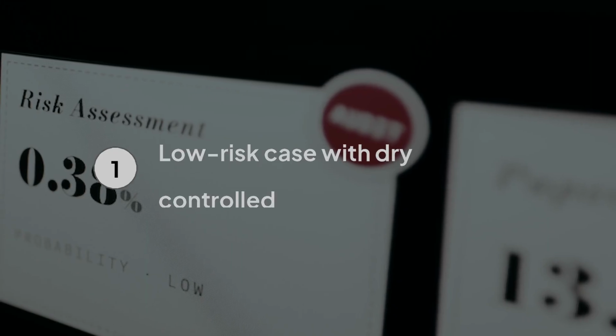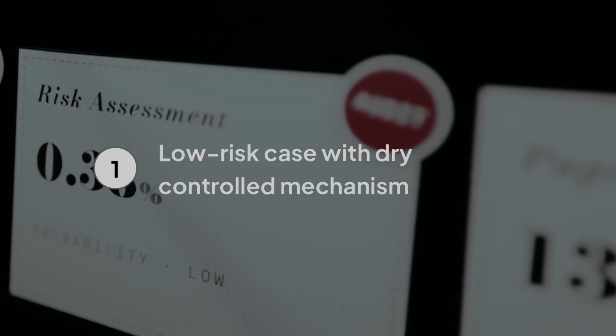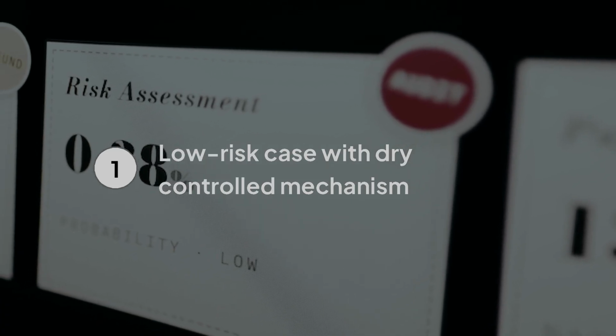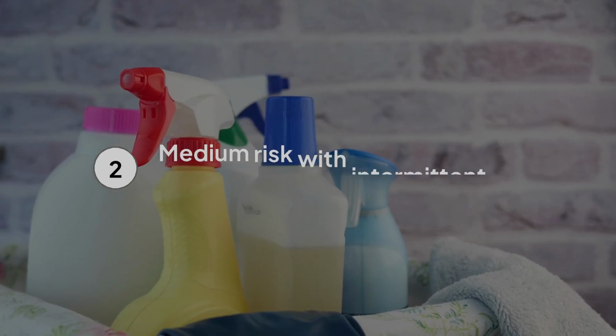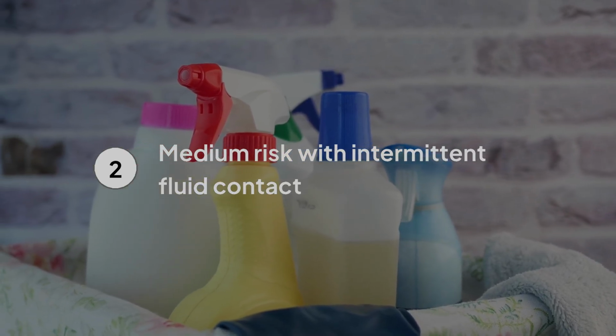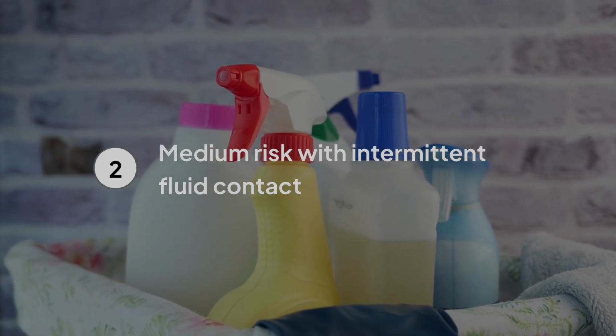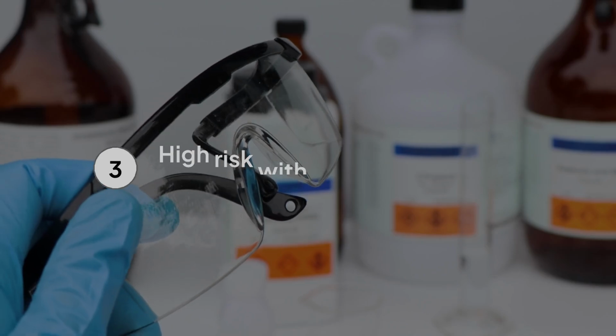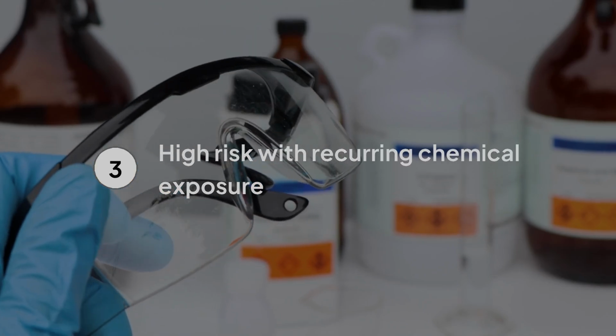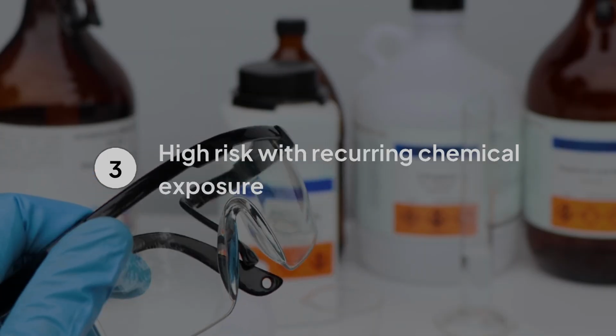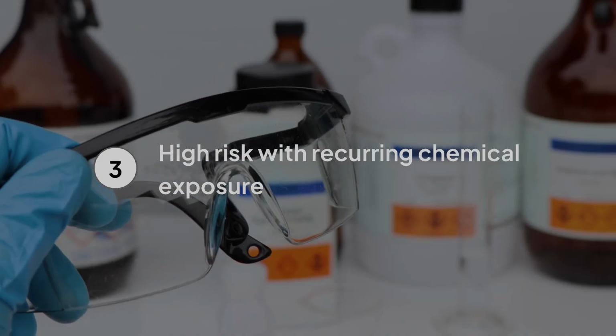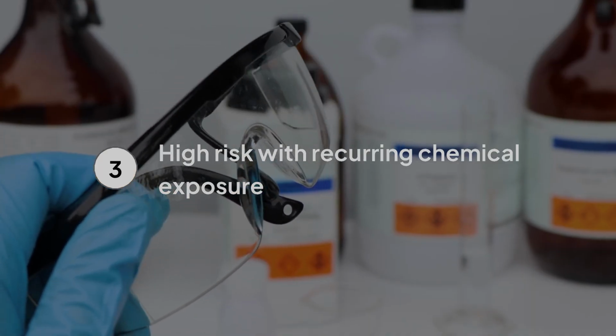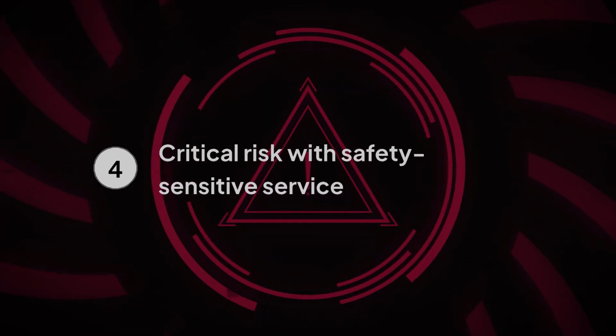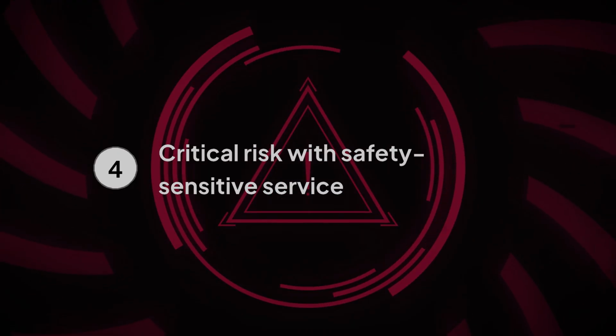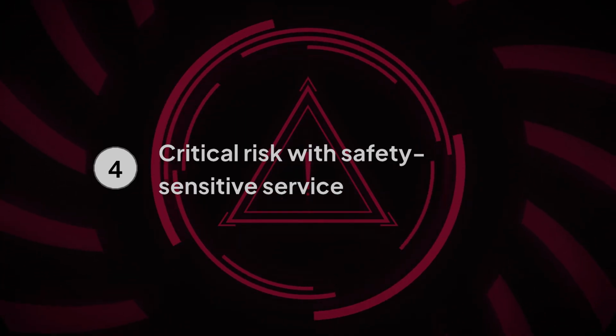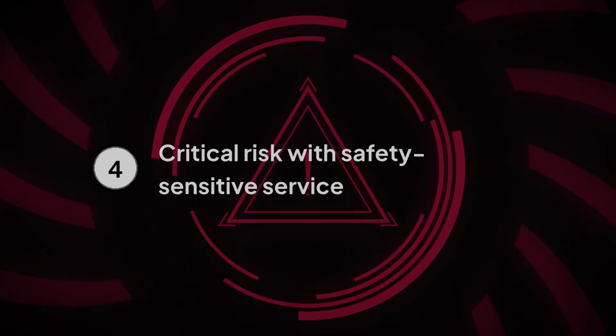A practical selection process starts by assigning application risk. A low-risk case is a dry, controlled mechanism without aggressive media, where dimensional confirmation and a material declaration may be sufficient. Medium risk includes intermittent fluid contact or routine cleaning and calls for lot records, surface control, and sample review. High risk covers recurring chloride or chemical exposure, elevated temperatures, retained deposits, or tight crevices, requiring environment-specific testing or engineering assessment. Critical risk includes safety-sensitive service, uncertain exposure, long-term human contact claims, or regulated conditions that demand application-specific validation and quality evidence.